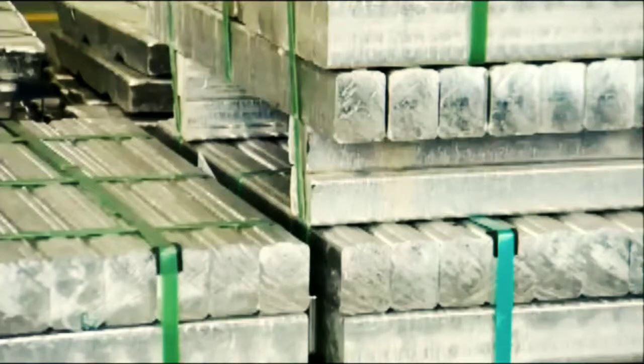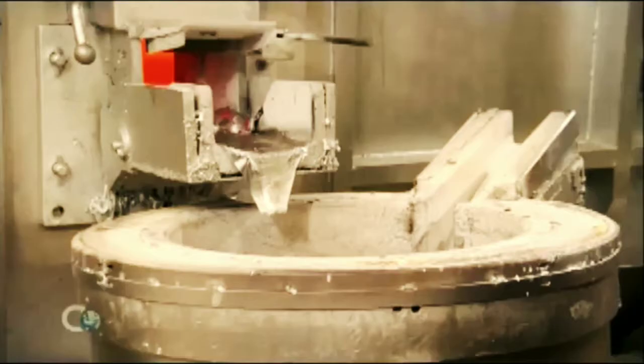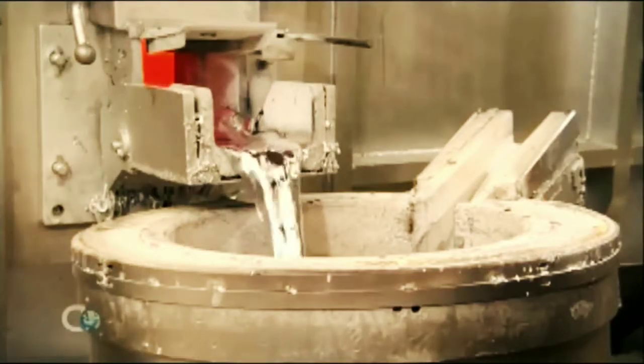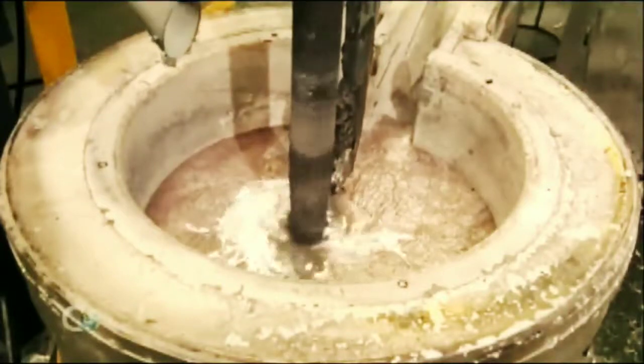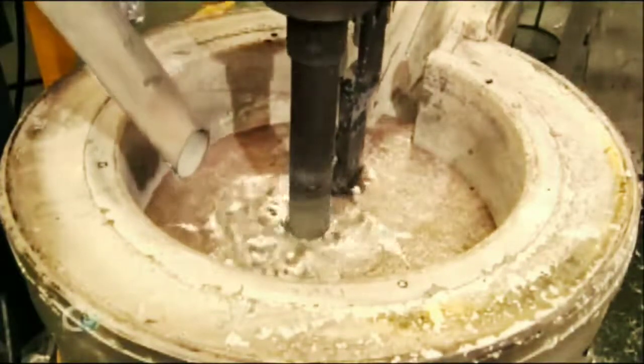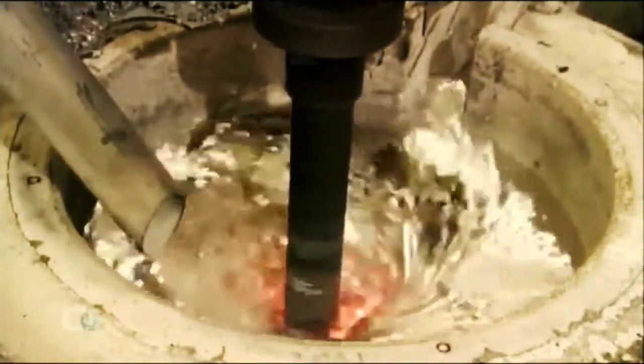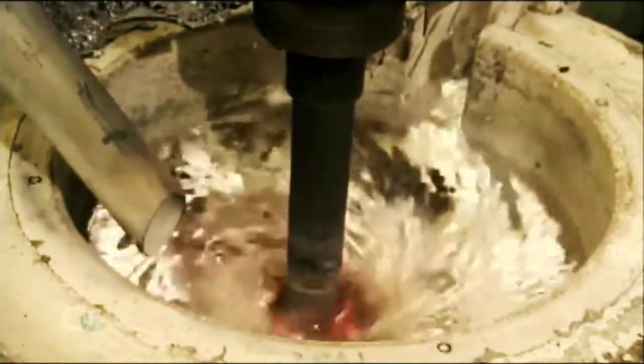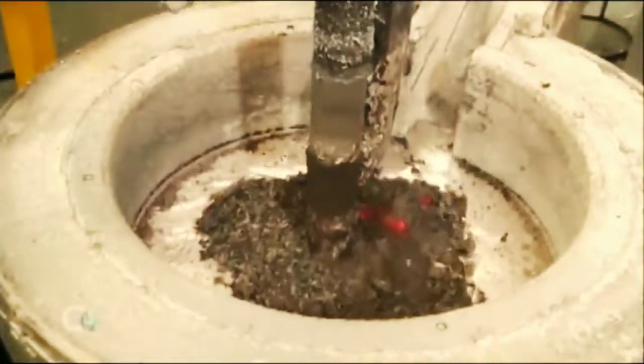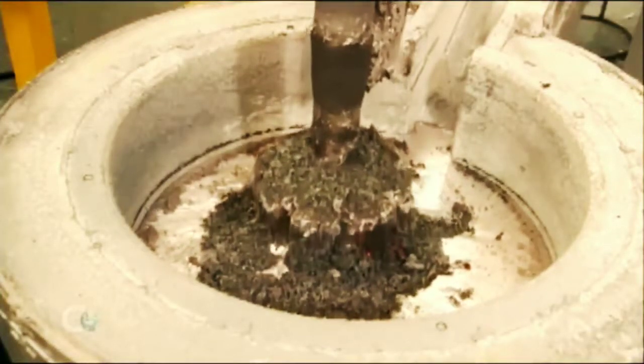Manufacturing them begins with high-grade aluminum alloy, containing 97% aluminum. A furnace heats the ingots to 750 degrees Celsius. They liquefy in about 25 minutes. The molten aluminum then flows directly to a mixer, in which they inject argon gas, which enables them to remove the hydrogen. This increases the density, making the aluminum less porous when solidified. After adding powdered titanium, magnesium, and other metallic elements to further strengthen the aluminum, they blend in flux, a chemical which draws aluminum oxide to the surface. They skim off this impurity along with the flux, and the liquid aluminum is ready for casting.